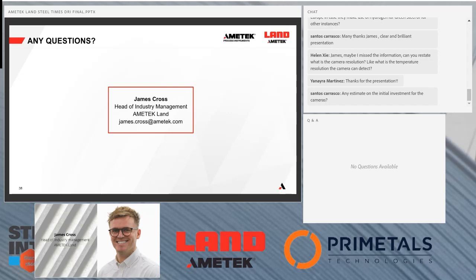Yeah, so camera resolution on the high definition is 1920 by 1080. I could be wrong. I'll share this presentation. So that's the pixel resolution. So say 3 million pixels. Each one of those pixels will give you an accuracy of about 0.5% of the measurement. So on a 1000 degrees C tube, we can give you an accuracy of plus or minus 5 degrees C. Sensitivity is about a degree, so it will detect changes of plus or minus 1 degree C.